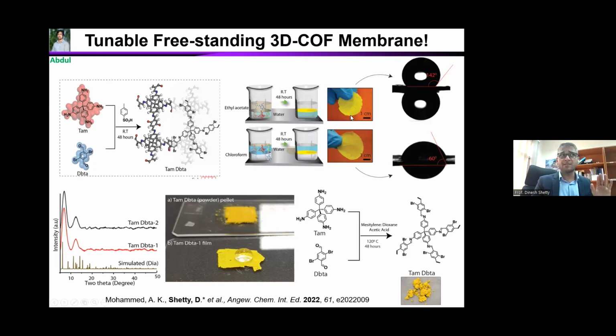But to our surprise, in the case of the ethyl acetate water system, we end up getting a membrane really hydrophobic in nature. You can see water is completely repelled. In both cases, we end up getting a 3D COF membrane. That is the first important step here. And then in the second case, what happened? With the same building blocks, when we just change the solvent from ethyl acetate to chloroform, we end up getting a kind of hydrophilic membrane. That was a surprising thing for us because it's the same building blocks, we didn't do anything. The method is different. Right? So then we tried to understand why this is happening.